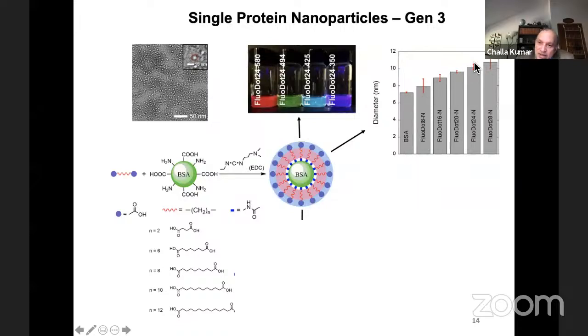There's a systematic linear improvement in the size and it correlates beautifully, meaning that we're able to make discrete particles that have enough carboxyl groups and then long chains on them, so the diameters match up quite nicely. So we can start with about 7 nanometers and it can go all the way to about 10 nanometers. So step by step, we're increasing the size of the particle using 2 covalent bonds at a time. And it is nearly impossible to achieve that kind of resolution, increasing the length by 2 carbon bonds at a time, right?